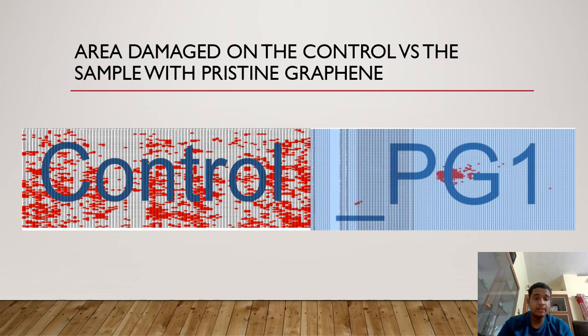Here is a secondary bit of analysis. The pictures here show the damaged areas by the simulated lightning strikes. So the control on the left has significantly more damaged area on the ultrasonic testing. The pristine graphene, on the other hand, has significantly lower area damaged. So what does this mean?